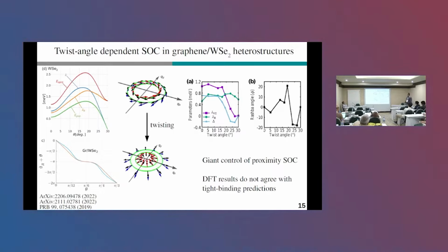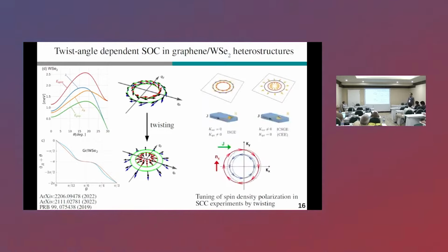So what is the consequence of this radial spin-orbit field? If you do spin-charge conversion experiments, which we have heard of today, and you have such a typical tangential Rashba field, then your spin density that you generate will be perpendicularly polarized to the charge current. This is known as the inverse spin galvanic effect or Rashba-Edelstein effect. No matter how you call it, it's the same mechanism.